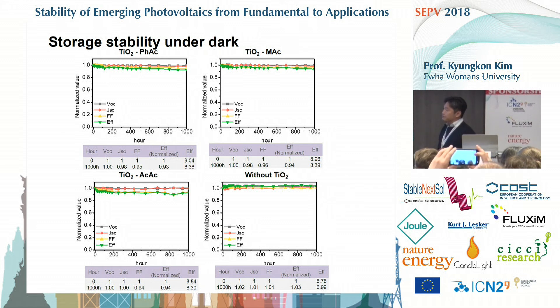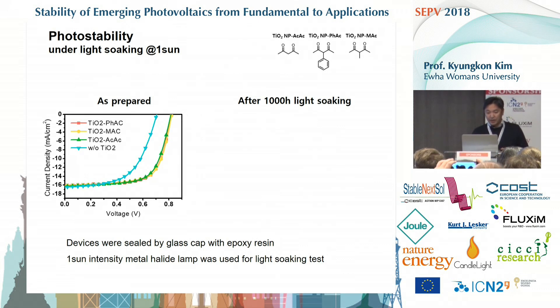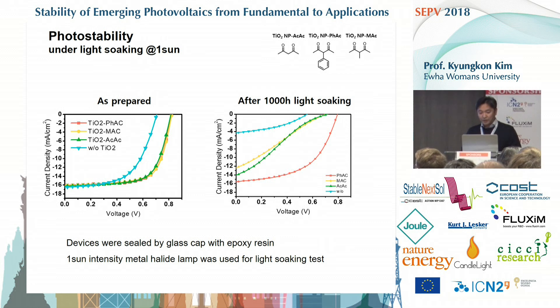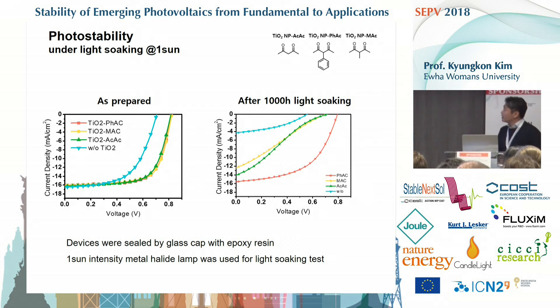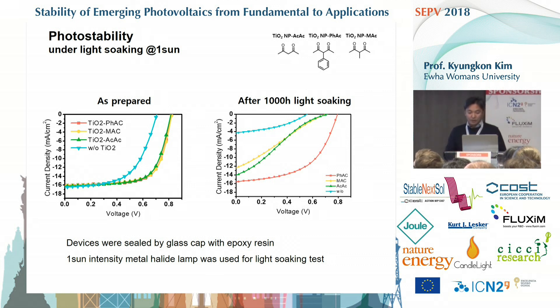As you can see, if you store in the dark, it is fairly stable until 1,000 hours. This is the previous sample, and after performing light soaking for 1,000 hours, there is a difference in performance. In the case of this phenyl-attached nanoparticle, it shows the best performance after 1,000 hours of light soaking. However, this methyl-acac coated titanium dioxide loses fill factor and JSC a little bit — losing the fill factor is the main cause of degradation of this device.